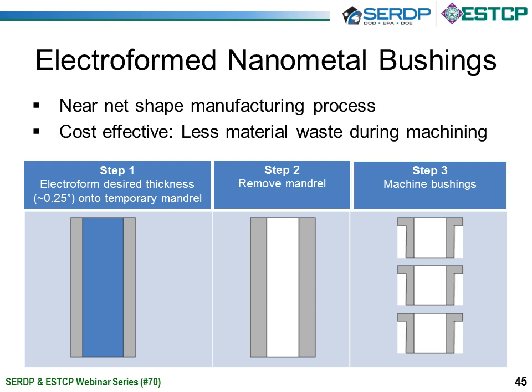So I'll go into the next slide. This is just a very simple schematic of the process. As I mentioned, sort of near net shape. It's quite cost effective, very little material waste. In contrast, copper beryllium is often machined from a block of material, which for a large bushing creates a lot of waste. Here we deposit the material onto the mandrel, remove the mandrel, and then do a little bit of machining to produce the bushings of a desired dimension.